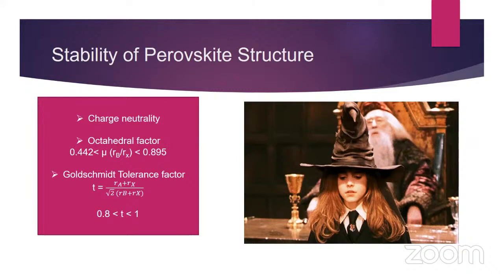Basically this tolerance factor decides the structure of the crystal. If the value of t is from 0.9 to 1, then the structure would be cubic. If the value of t is from 0.8 to 0.9, then the structure would be either orthorhombic or tetragonal. And if the value of t is exactly 1, then it would be a perfect cubic structure. If the value of t is higher than 1, then we can say that this A site cation is too big to be fitted in the perovskite structure. And if the value of t is lesser than 0.8, then this A site cation would be too small for the perovskite structure. So basically, the Goldschmidt tolerance factor and the octahedral factor work as the sorting hat.